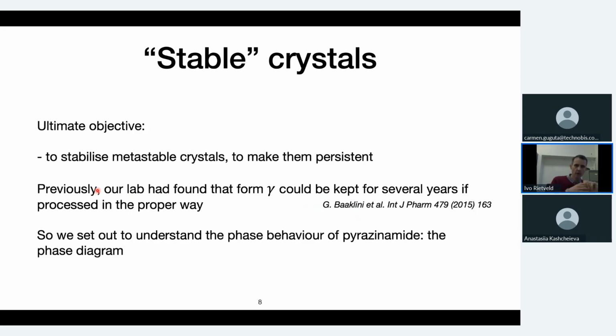But what we found in our lab was that if gamma would be spray dried with certain additional compounds like dimethylurea, for example, these gamma crystals would stay and remain intact for years and not convert into anything. So the question is then, what is going on here? And that, of course, was one of the axes of the research.